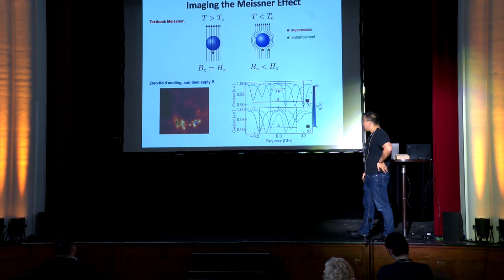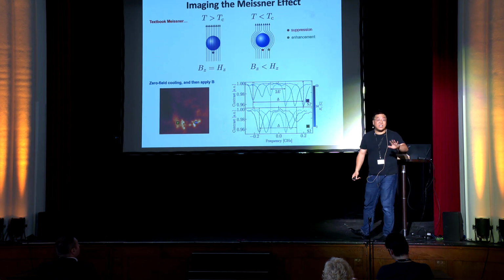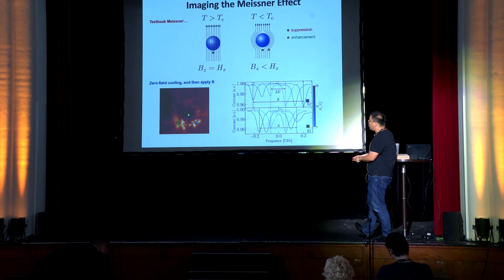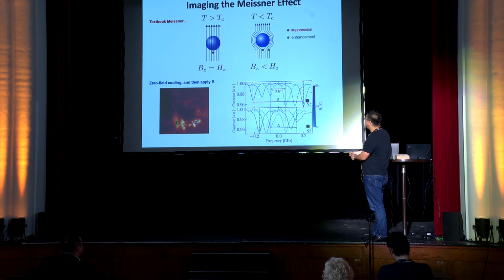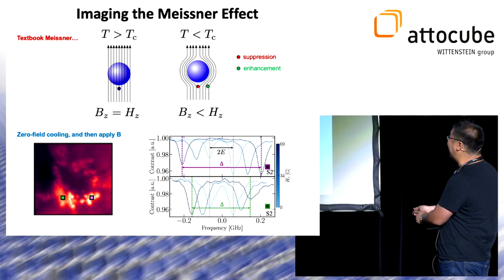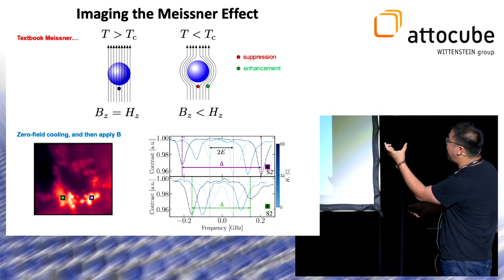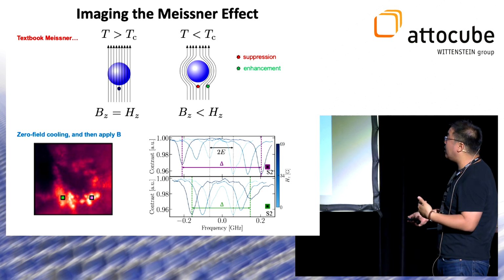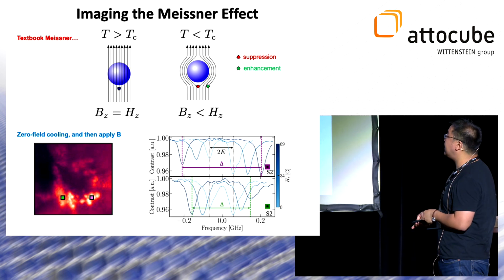So just to give a quick sense of what the raw signal looks like. Here's 2 different points on a sample. It's actually not the same BISCO sample, but doesn't matter too much. And as promised, as a function of increasing magnetic field, so the curves get darker and darker for an increasing value of the applied magnetic field Hz, you see that the Zeeman lines, the splitting between the plus and minus 1 states, gets larger and larger and larger. And in different regions, it may get larger and smaller in different ways.